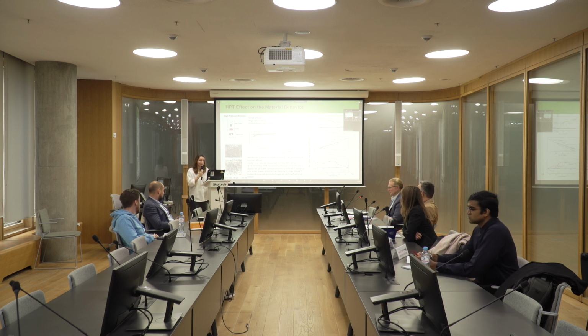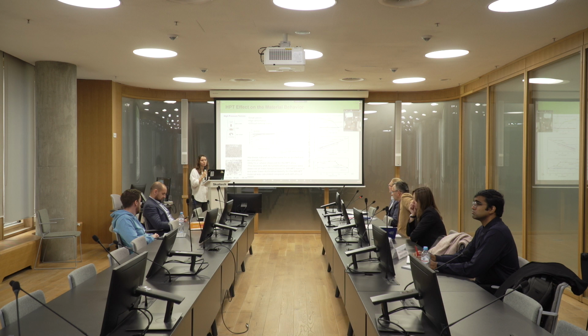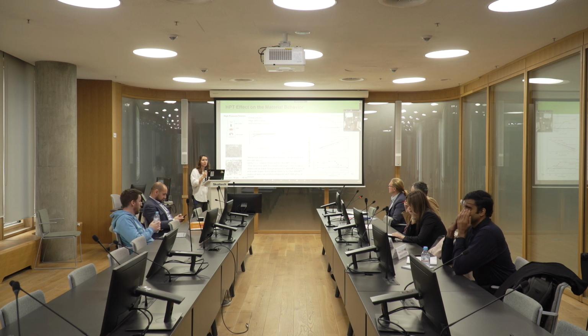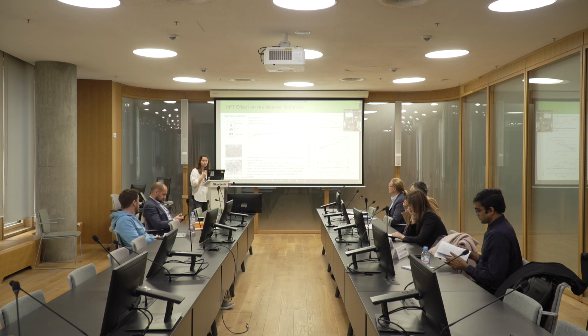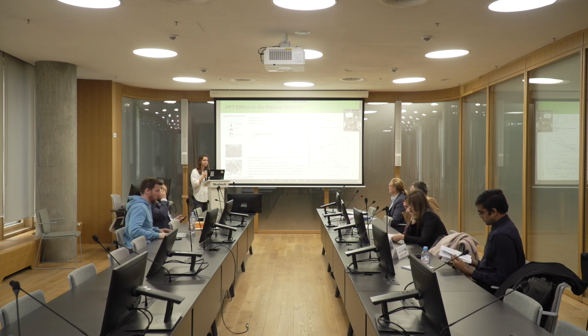I'm sorry, could you repeat the last? My comment is that many of these alloys are prone to sigma phase precipitation, particularly when you deform to large strain and then anneal it. So this sigma phase precipitation is accelerated. Could you please comment whether you have observed any sigma phase precipitation? In our materials, in the as-built state, we didn't observe sigma phase precipitation, and even after the HPT process. But I should mention that other work demonstrates the material arc melted or with further procedure.